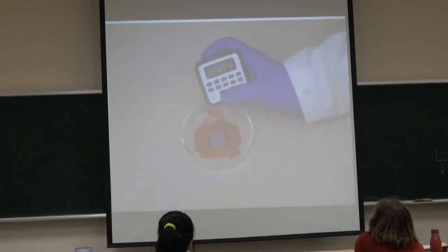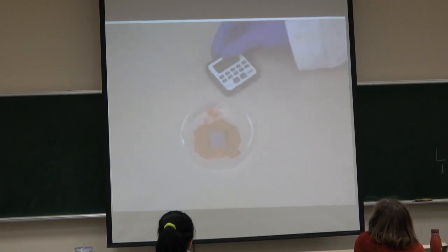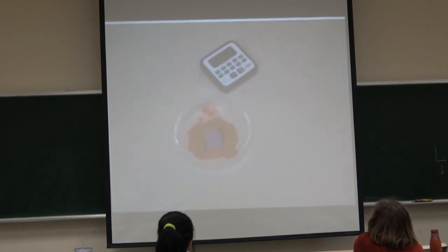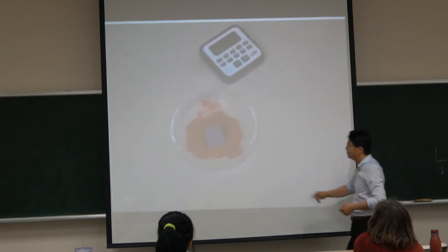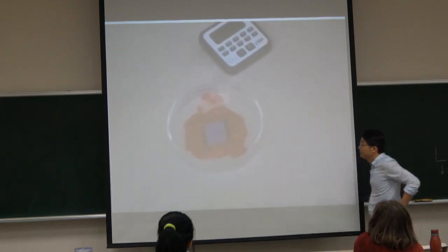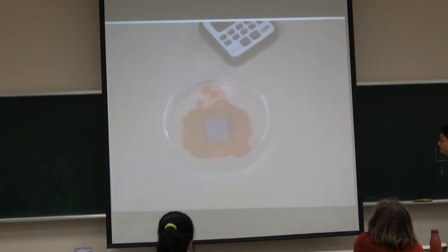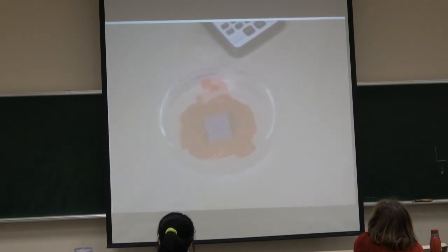Step 4. Let the slide soak in the juice for 10 minutes. The film should be stained bright purple. If you can see any white titanium dioxide remaining on either side of the glass after 10 minutes, put the slide back into the dye for another 5 minutes. Now is a good time to start on part 5, carbon coating the counter electrode.